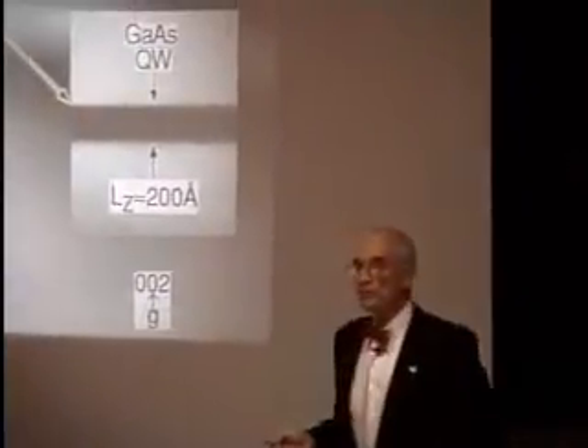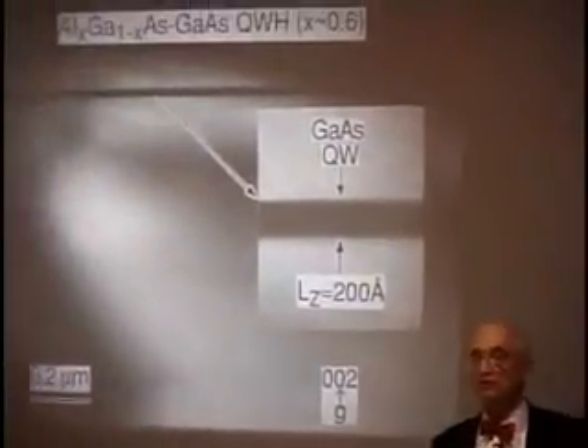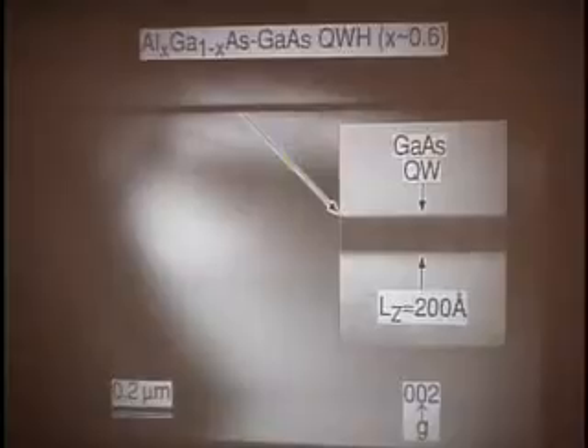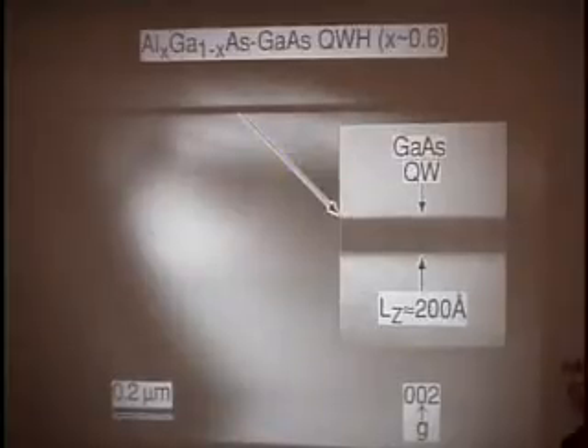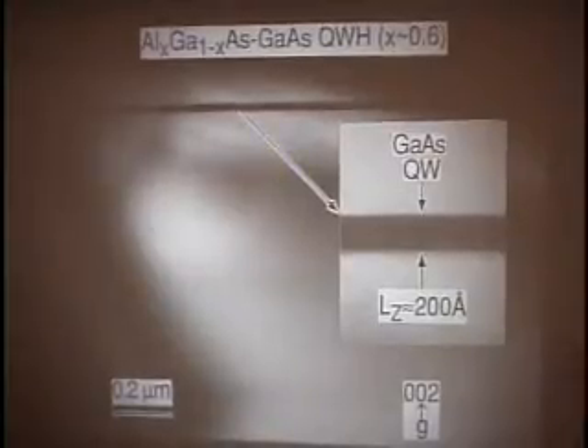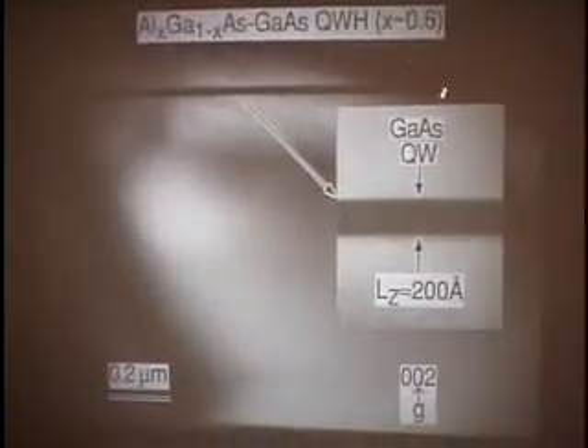But Dupree and his MOCVD machine could grow better for us. So when we showed the world our LPE quantum wells, Dupree was willing to go into his MOCVD machine and grow us some stuff like this. Here's a thick piece of aluminum gallium arsenide, 60%. Here's a 200 angstrom gallium arsenide layer, another 1,000 angstroms of aluminum gallium arsenide.